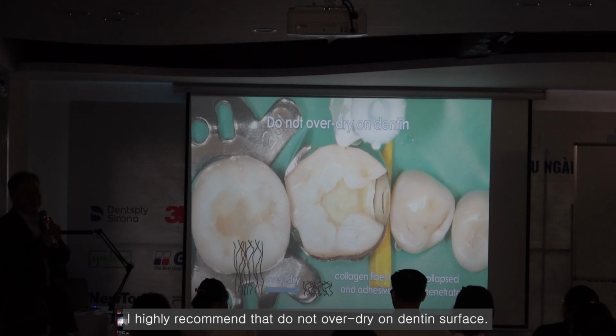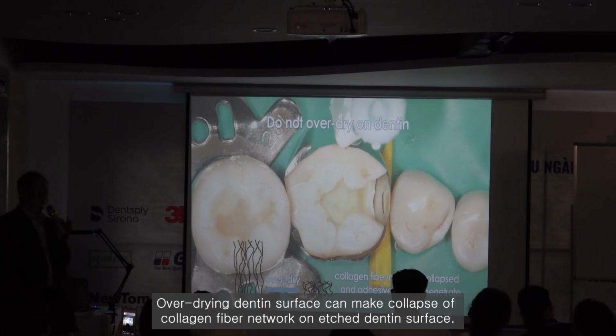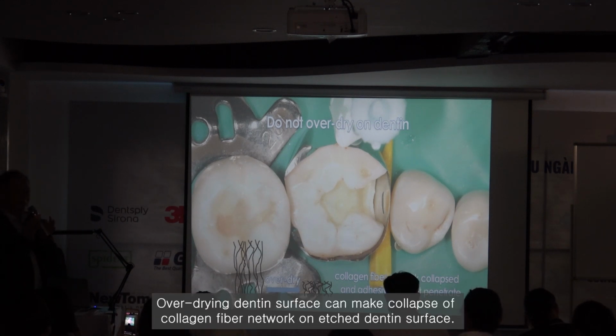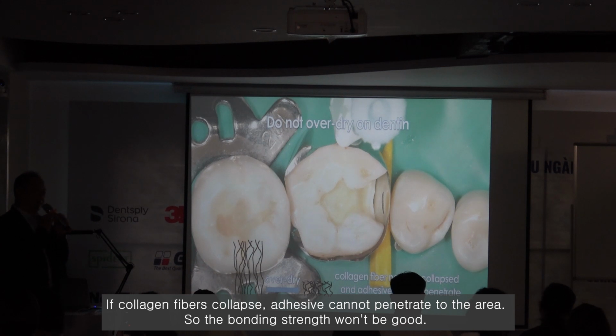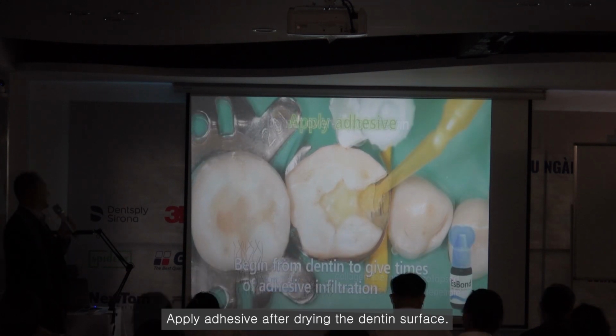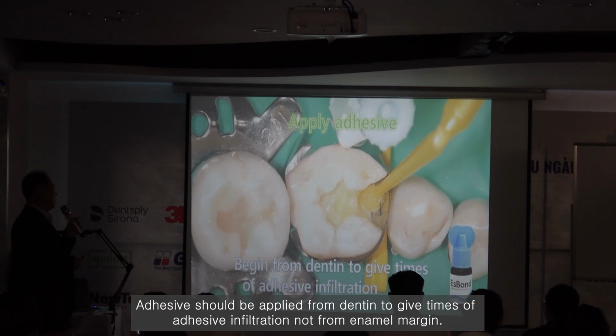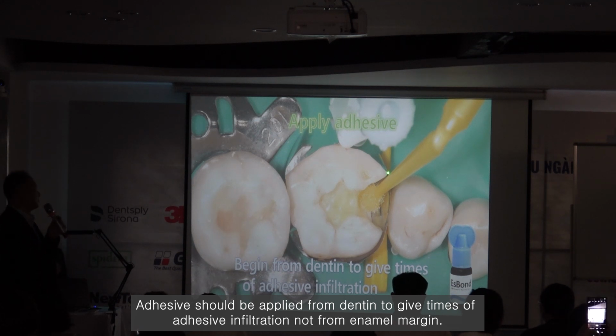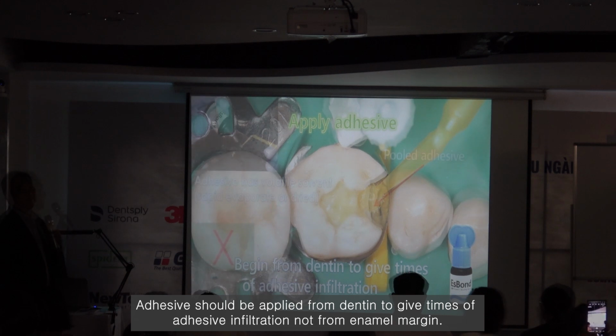But I highly recommend that you do not over-dry the dentin surface. Over-drying the dentin surface can cause collapse of the collagen fiber network in the etched dentin surface. If the collagen fibers collapse, adhesive cannot penetrate to that area, so the bonding strength will not be good. Apply adhesive after drying the dentin surface. Begin from the dentin to give more time for adhesive infiltration, not from the enamel area.